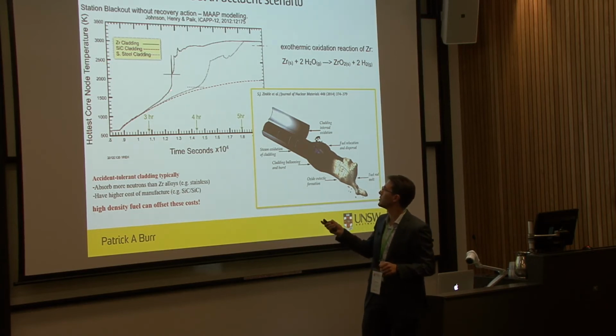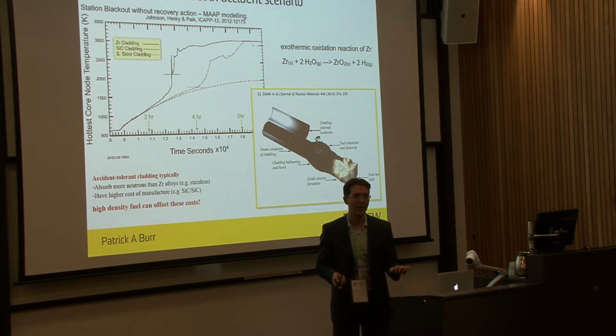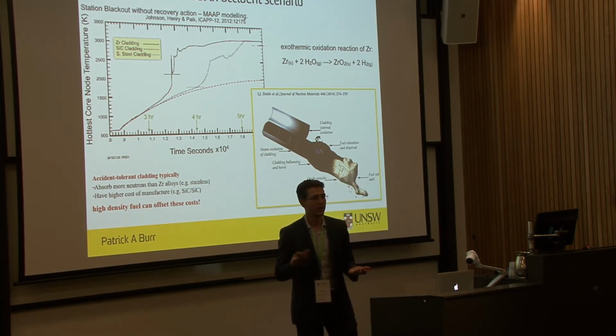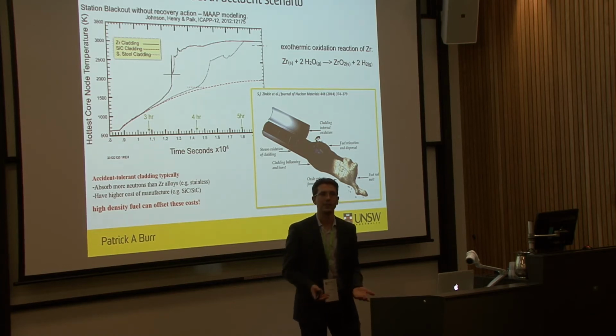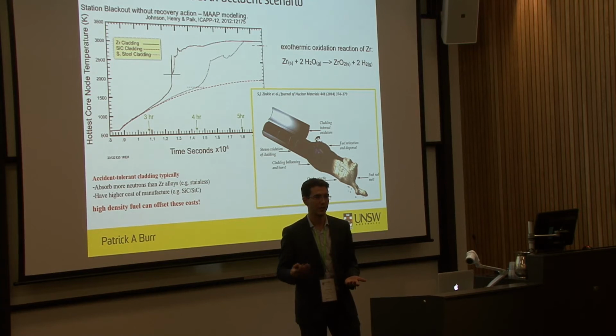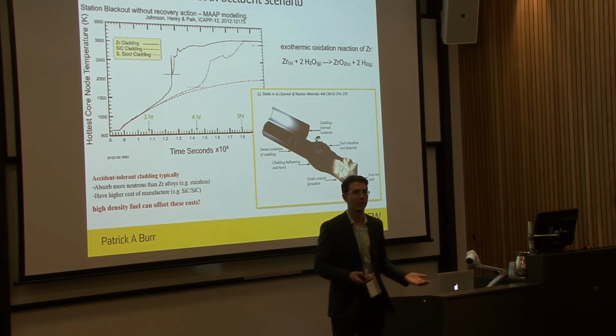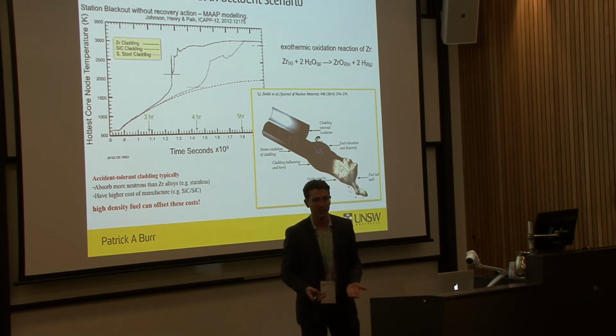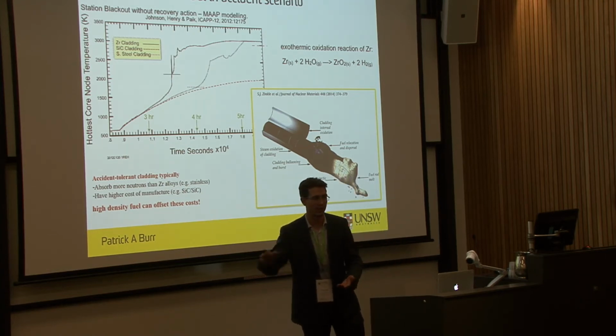However, if you look at what actually happens to zirconium, which is this black line, you see that it's super parabolic. It heats up faster than parabolic. And the reason for that is that if you get a metal and you heat it up, you're increasing the oxidation rate of that metal. And that's true for any metal. Unfortunately, oxidation of a metal is actually an exothermic reaction. So you're producing heat, and that heat contributes to the increase in temperature, which then increases the rate of oxidation, which then produces more heat, and so on.